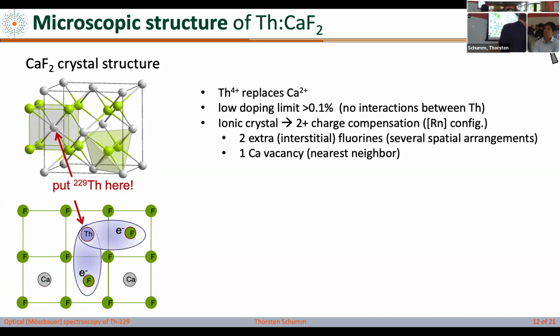And there are essentially two ways it can do this. Either it puts two additional fluorines in the spatial vicinity, or it omits a calcium in a neighboring cell. Okay, these are essentially the two ways the crystal can do this. We call these two interstitial fluorines, and we call this a calcium vacancy. So in defect physics, this is a known thing. We're not inventing anything here. We're just reading books that were written a long time before I was born, actually.